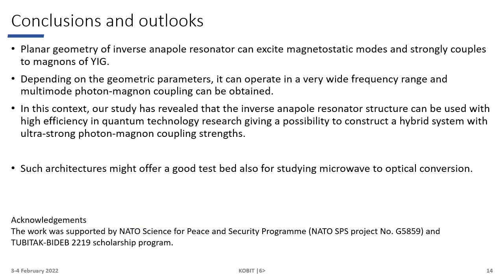In conclusions and outlooks, the planar geometry of the inverse anapole resonator can excite magnetostatic modes and strongly couples to magnons of yttrium iron garnet. Depending on the geometric parameters, the inverse anapole resonators can operate in a very wide frequency range and multimode photon-magnon coupling can be obtained. In this context, our study has revealed that the inverse anapole resonator structure can be used with high efficiency in quantum technology research, giving a possibility to construct a hybrid system with ultra-strong photon-magnon coupling strengths. Such architectures might also offer a good testbed for studying microwave to optical conversion.